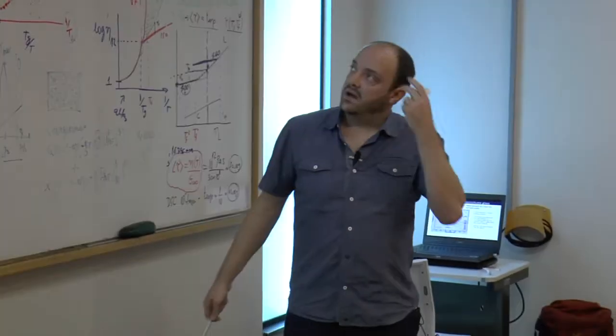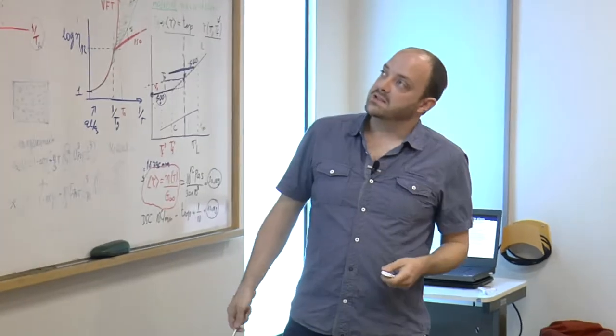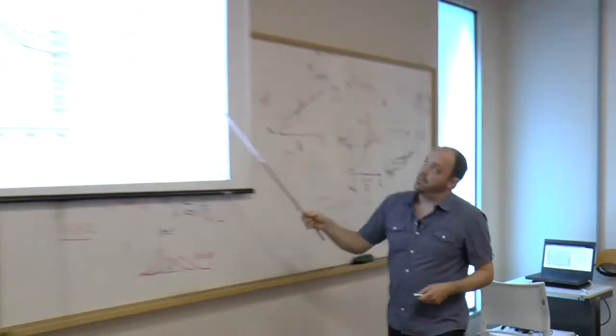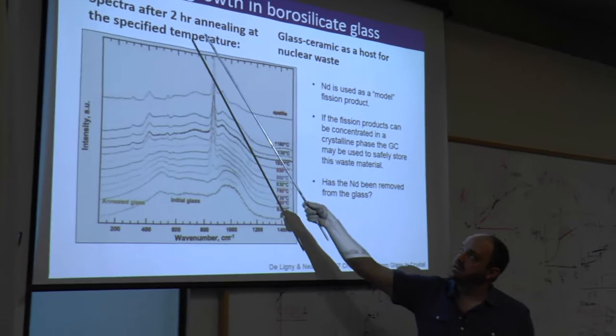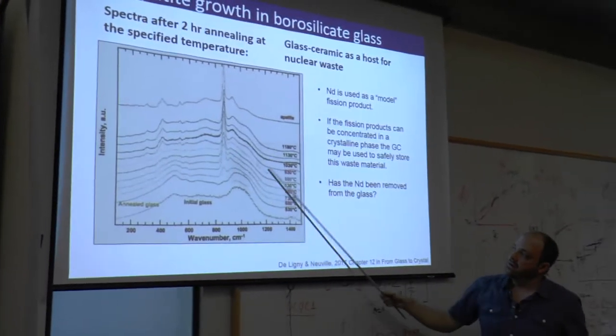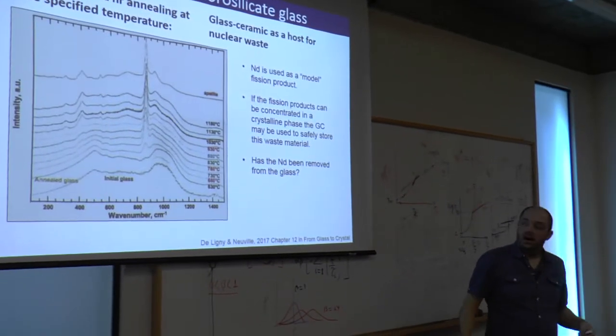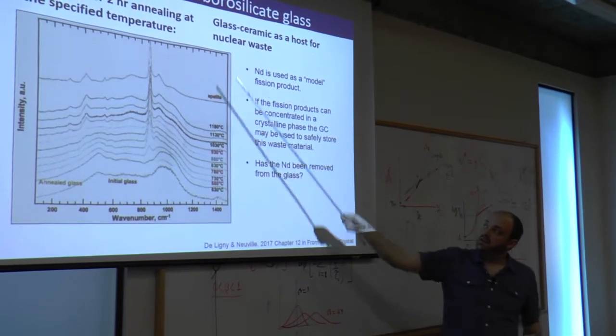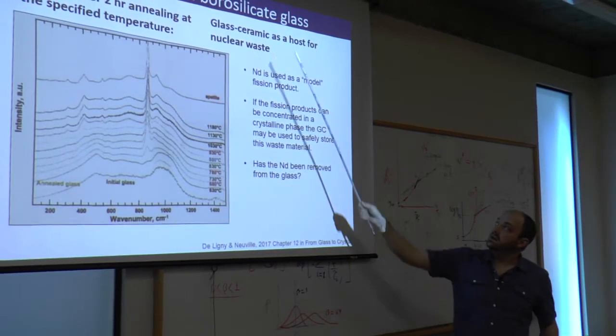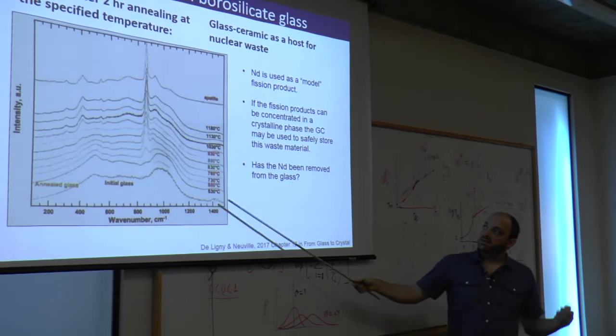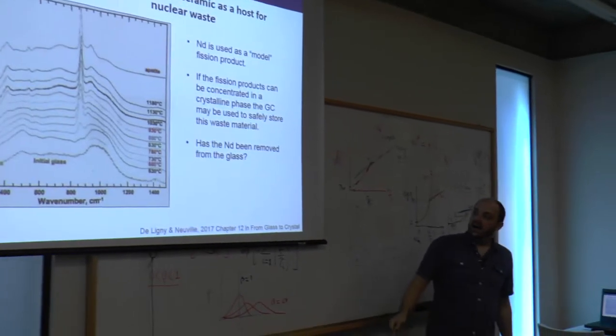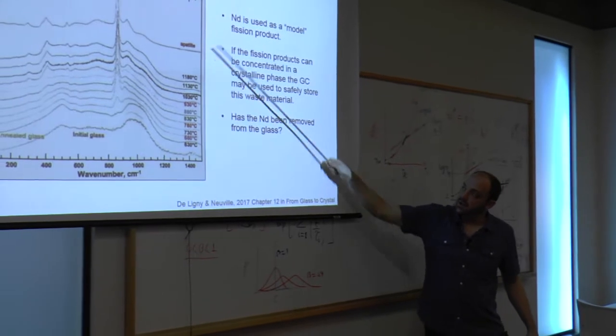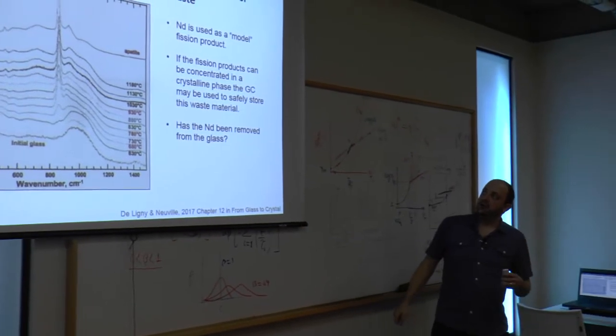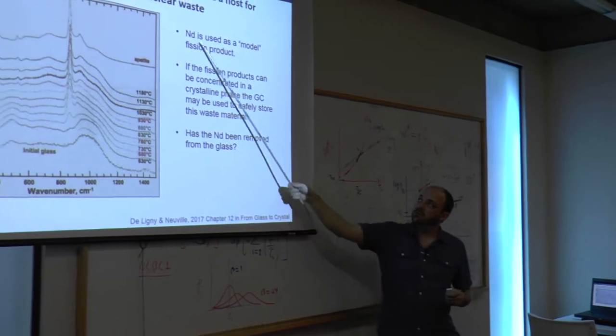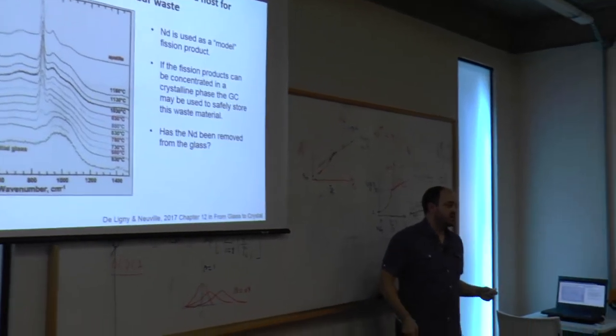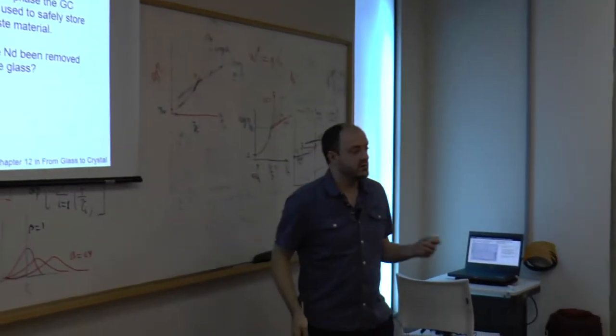Another example, I actually quite like this example. This is apatite in a borosilicate glass. Apatite is a calcium phosphate. And all of these spectra are taken in glasses where they've mixed a little bit of apatite composition, calcium phosphate, into the borosilicate. And they've annealed the glass for 2 hours at the various temperatures you see here. They also added a little bit of neodymium. This glass composition has actually been proposed for the storage of nuclear waste.